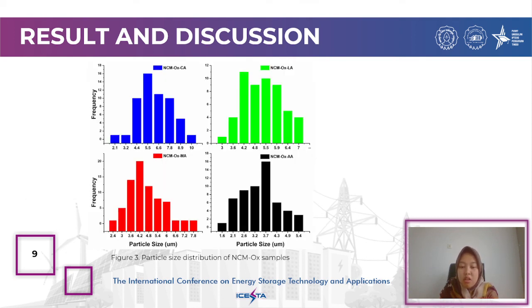Figure 3 shows the particle distribution chart of the NCM oxalate samples. Based on the figure, NCM oxalate from citric acid and NCM oxalate from malic acid have particle size ranges of 2.1 to 10 micrometer and 2.4 to 7.8 micrometer. Meanwhile, NCM oxalate from lactic acid and acetic acid have particle size ranges of 3 to 7 micrometer and 1.6 to 5.4 micrometer.